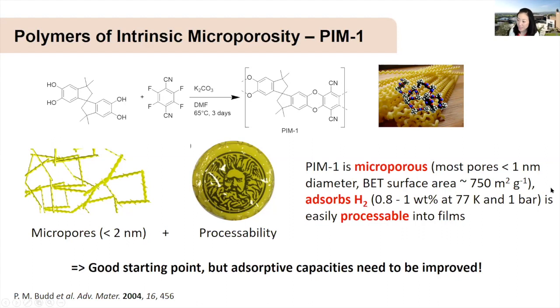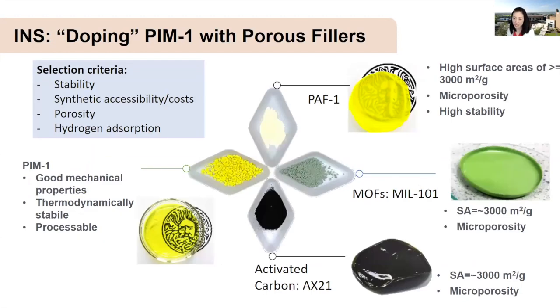But the hydrogen storage capacity is relatively low. So for our application, this is a good starting point, but the hydrogen capacity needs to be improved. To improve the capacity, we introduced porous fillers into its membrane system. These are three porous fillers, and they have extra high surface area, microporosity less than 1 nanometer, and they are highly stable. They are perfect. The only problem is they are in powder form, and powder is very difficult to manage in industry. So we combined the good processability of the membrane with the high hydrogen storage capacity of the porous fillers to form the composite membrane. Those three composite membranes we synthesized successfully.